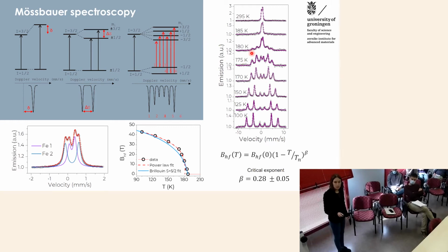Following these experiments, we can also plot the order parameter, which in the case of Mossbauer is the magnetic hyperfine field splitting. Plotting it, we can follow the order parameter across the transition. What we find is that this follows a power law with a critical exponent close to 1/3. That is what we expect for a critical transition of an Ising system, so this is consistent with a critical transition of a system with uniaxial anisotropy. This is something that has not been shown for single crystals. So at least we knew that in our films there was mostly one phase, ordering with a second order type transition.